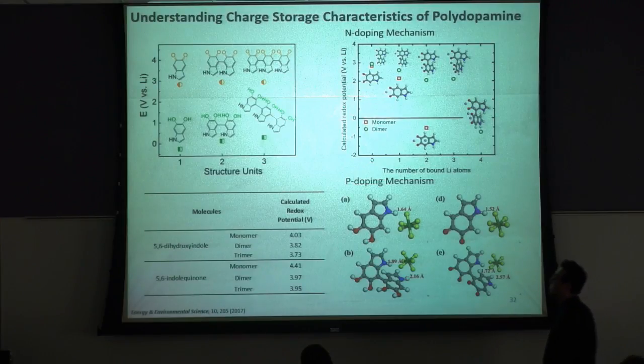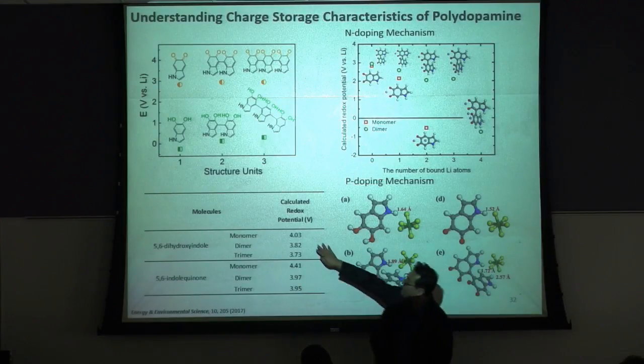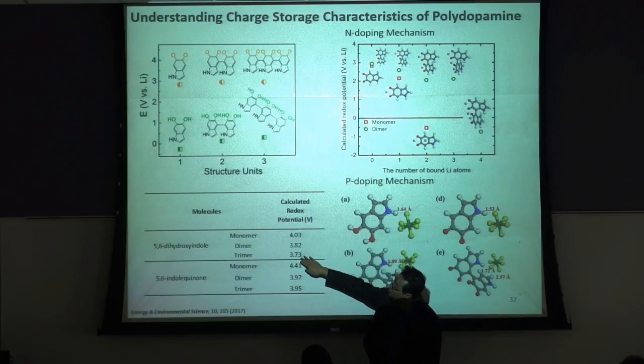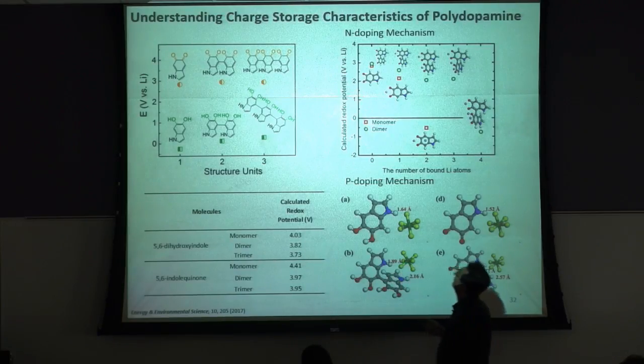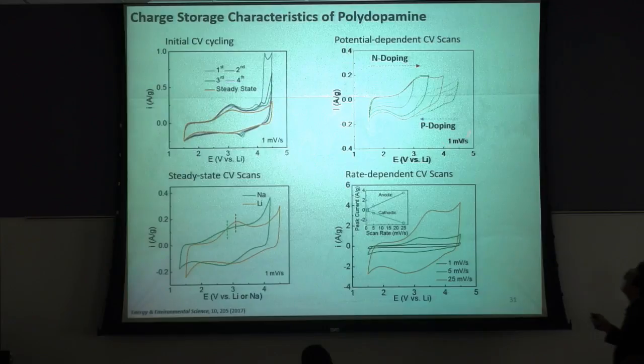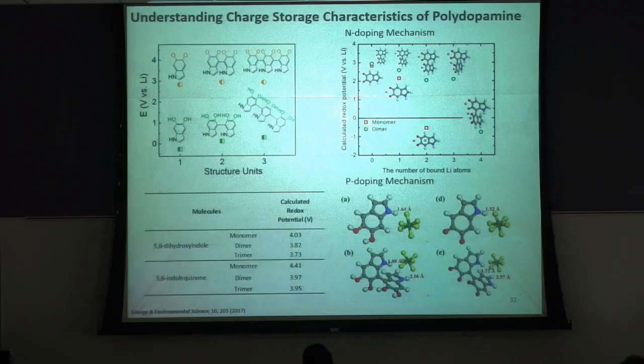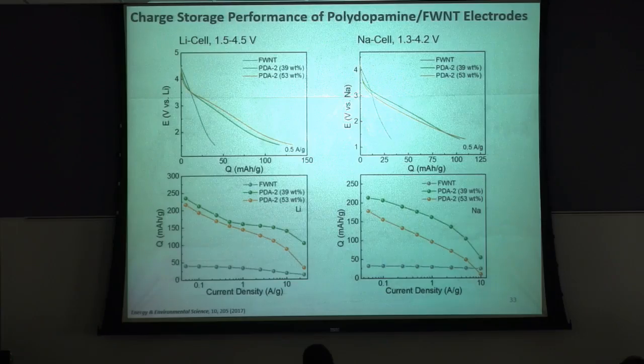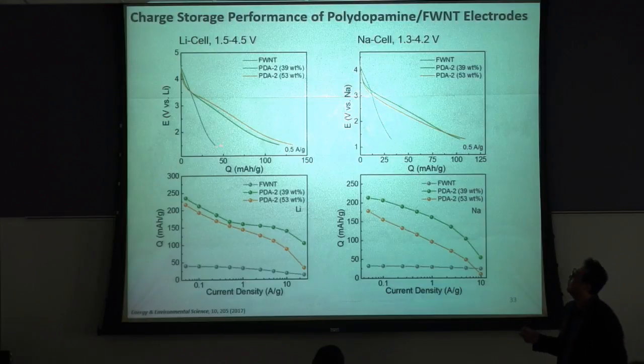So then the calculated redox potential is in the range of around 4 volts, right? From 3.7 to 4 volts. Then if we see this kind of CV scan, we can see this kind of redox features. This is related with the p-doping mechanism with the anion, so electrolyte anions.